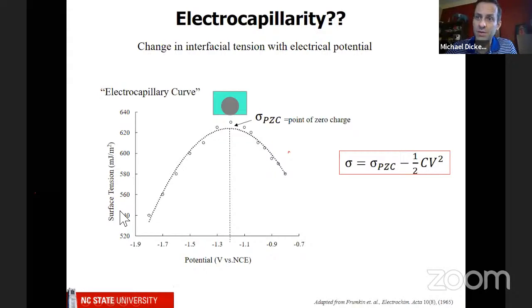This is a plot of surface tension, so again, the larger the surface tension, the more spherical the droplet's going to be, versus potential. If you wanted to lower the surface tension of a liquid metal, one way you can do it is to apply a potential. If you apply a positive potential to the metal, that should attract negative ions from solution, which are these red negative charges. And if you think about it, this should look like a typical circuit element, which is a capacitor.